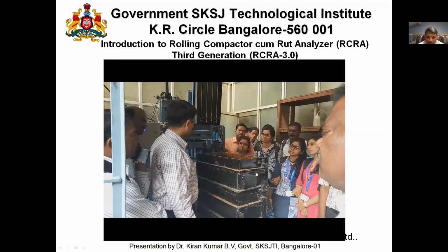If there is a new material which has come in between, for example, we are doing CTB and CTSB now, in 2018 IRC 37, cement treated base and cement treated sub-base, and we introduce such a pavement layer with the existing other materials like BC and DBM, and we do the rutting test, how will the rutting test results come with CTB and non-CTB, the conventional pavement? For that, we don't have to wait, construct a test track, spending lakhs of rupees, and do the test. This total model box also has scope for the introduction of embedded strain gauges. We have strain gauges which can be embedded, and they will give me the strain values coming at the interface of these layers.